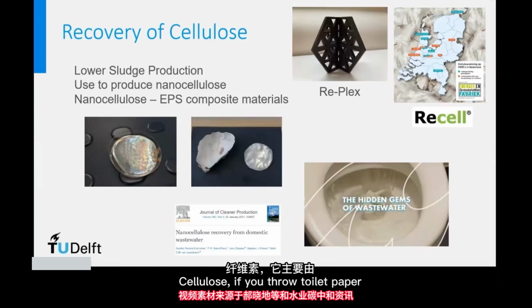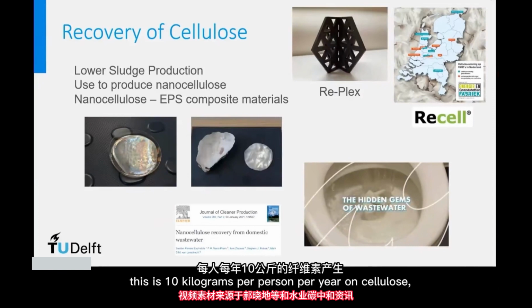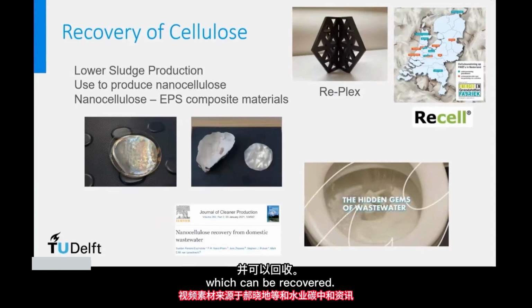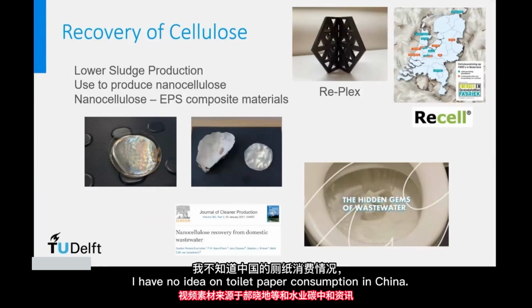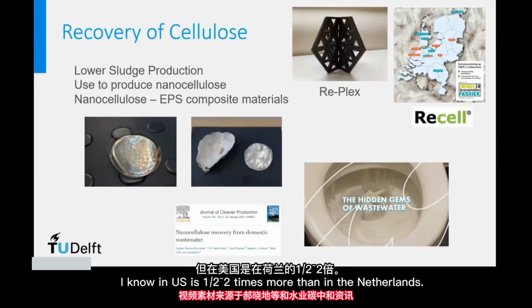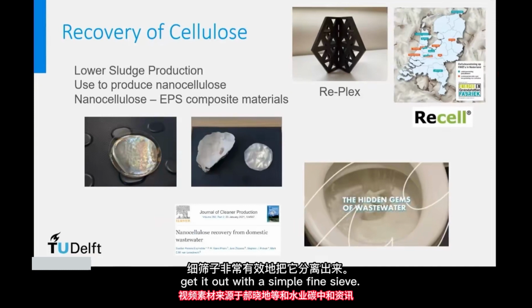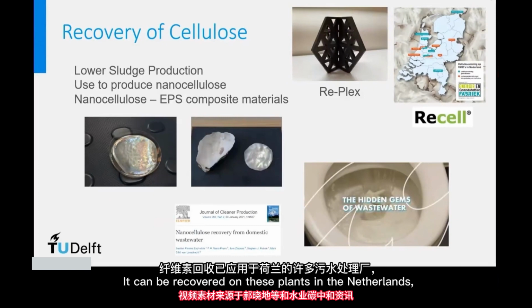Cellulose: if you throw toilet paper in the toilet and you flush it away, in the Netherlands, roughly this is 10 kilograms per person per year of cellulose, which can be recovered. So that's a huge amount. I have no idea on toilet paper consumption in China. I know in the US it's 1.5 to 2 times more than in the Netherlands. You can very efficiently get it out with a simple fine screen, a sieve, sorry, not a screen, a sieve. The technology is there. It can be recovered.